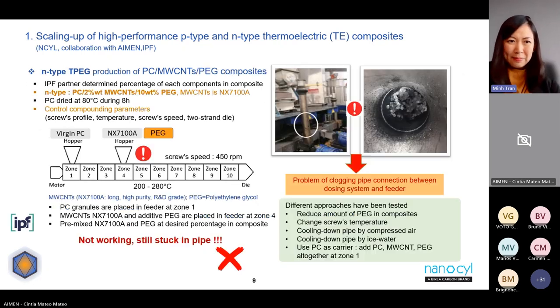Next slide, please. Concerning the N-type, we have quite a challenge, because the recipe has a third component, the additive polyethylene glycol, PEG, in the composite of polycarbonate and multi-walled carbon nanotubes. We had quite a big difference in melting temperature between polycarbonate, around 230 degrees Celsius, and PEG, around 65 degrees Celsius. Thus we had a blockage of the extruder between the hopper and the extruder throat.